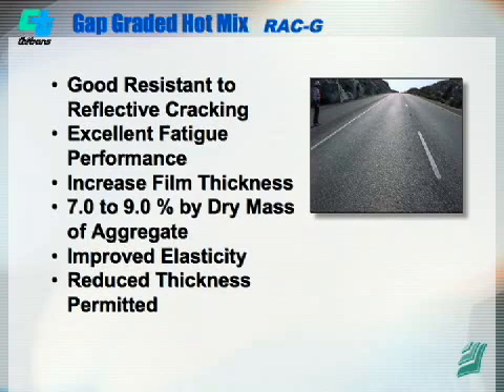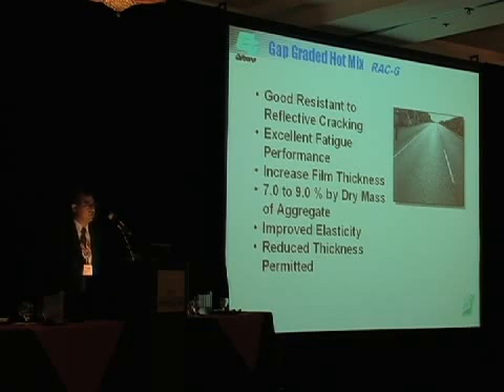So the RAC, the rubberized asphalt concrete gap-graded, is excellent in fatigue and reflective cracking behavior. We've done many tests using the bending beam test, using reflective cracking tests, in addition to the HVS, heavy vehicle simulator, all indicate the excellent behavior of asphalt rubber gap-graded. The binder content is pretty heavy, about 7 to 9%. And we have utilized this in reduced thickness. We have reduced thickness design based on its performance. The fatigue laboratory tests and reflective cracking tests have shown that it's more than 10 times better than conventional density-graded asphalt concrete, which has helped us develop the design guides reducing the thickness by about 50%.